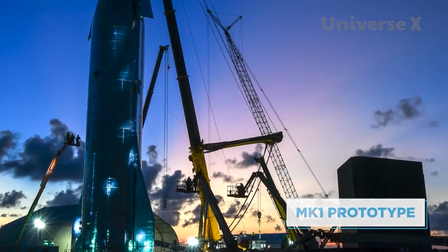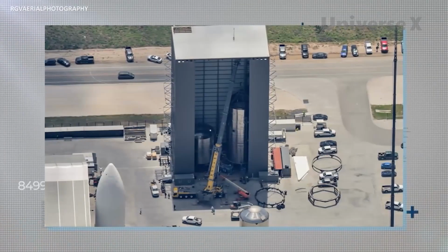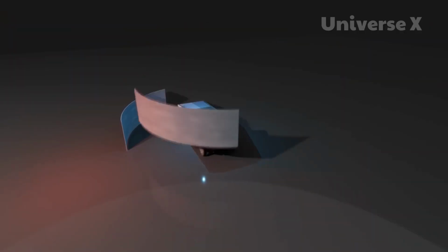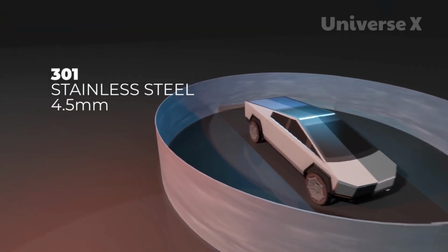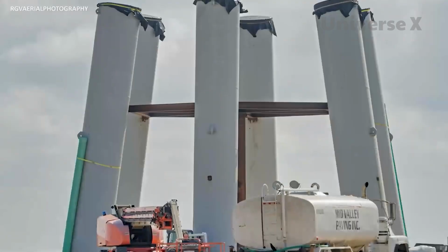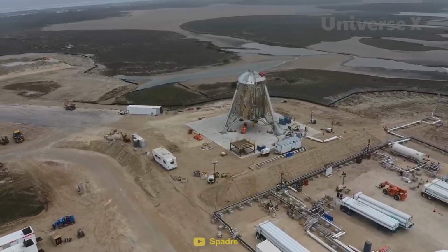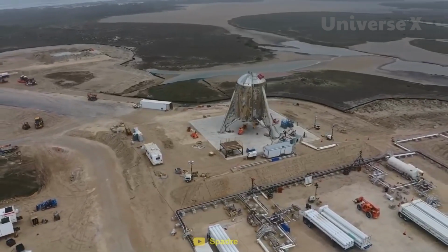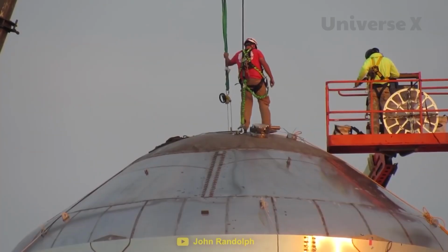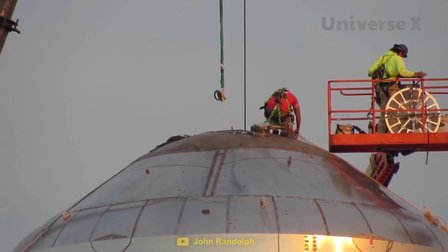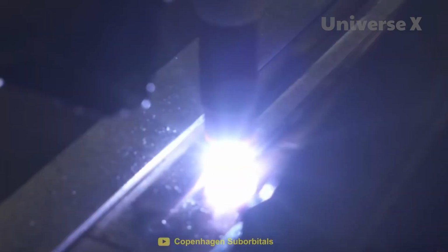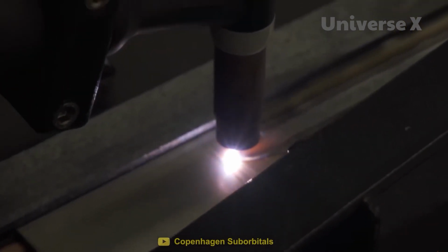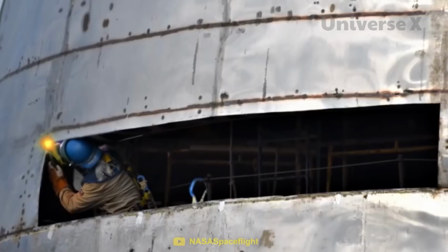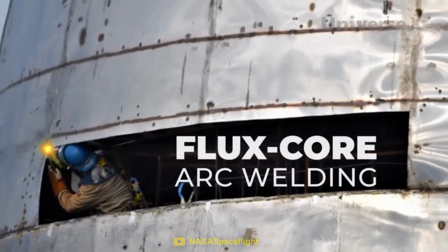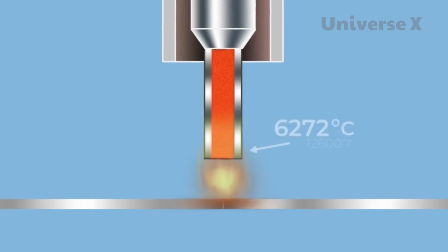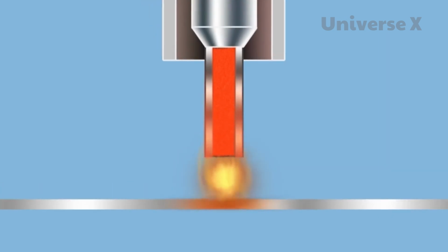Despite the theoretical advantages of flux core welding, the reality was far from ideal. The Starship crew, contracted from a water tower company, lacked experience in building rockets, and the welding standards were consequently subpar. The lack of a proper factory environment, with most welding taking place outside in a large tent, further exacerbated the issue. The welds on the first Mark I prototype were heavily corroded, with cracks and rough edges on the surface. To address these issues, SpaceX employed a grinding process to smooth out the welds, making them flush with the surrounding surface. While this may have appeared to be a cosmetic fix, it was actually a crucial step in strengthening the welds.